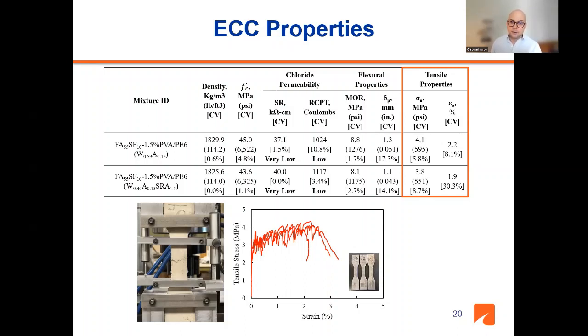And you can see also, for an illustration, I'm showing the test results for the material without the SRA admixture. These are 3 specimens that were tested for each case. And you can see that strain hardening behavior that I was talking about, with all these multiple peaks right here, which are all these tiny cracks that are generated in the process of damaging this specimen.